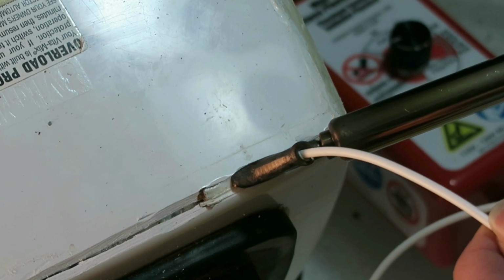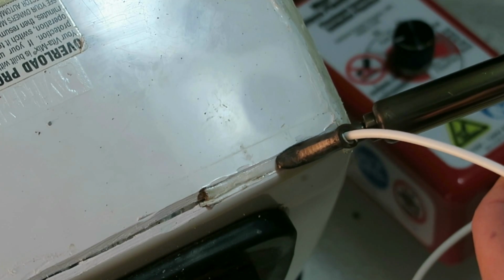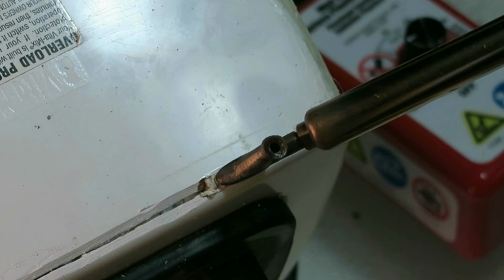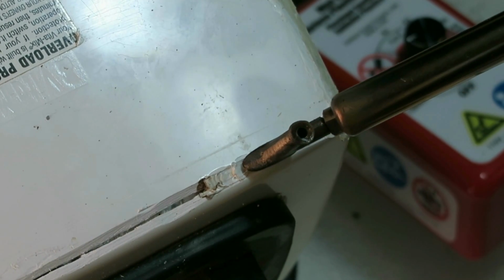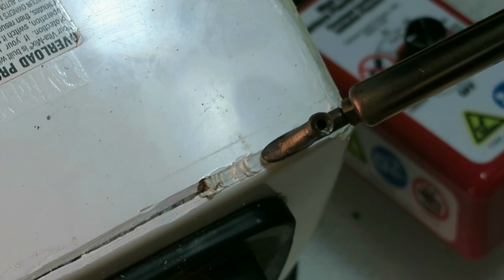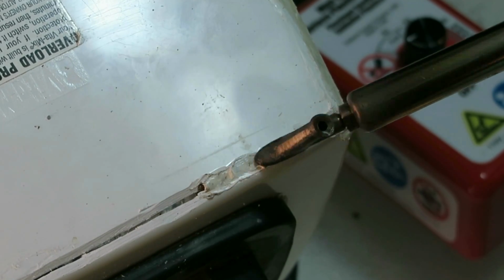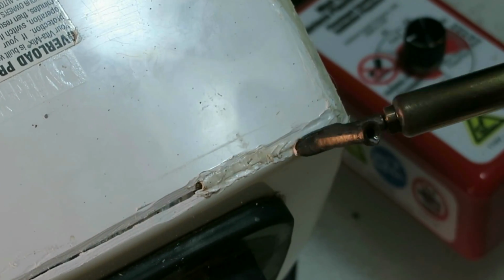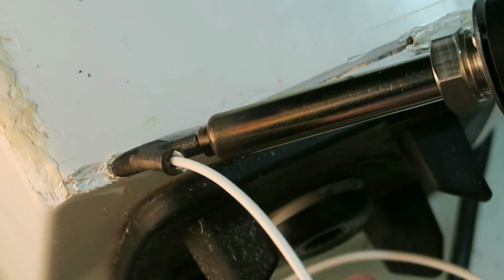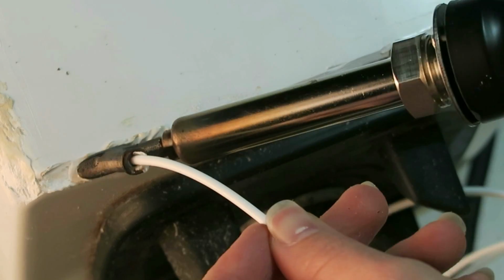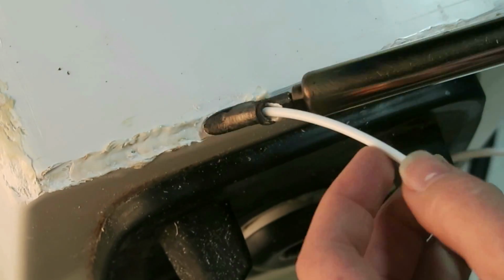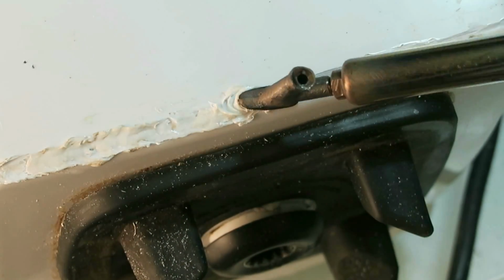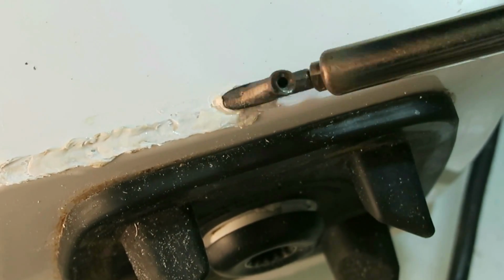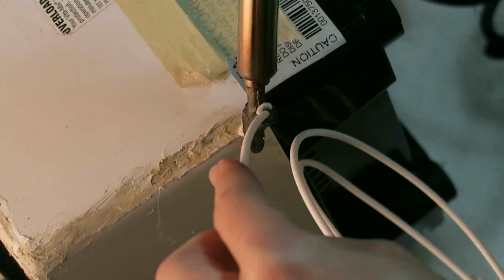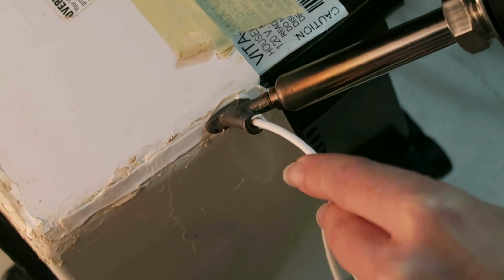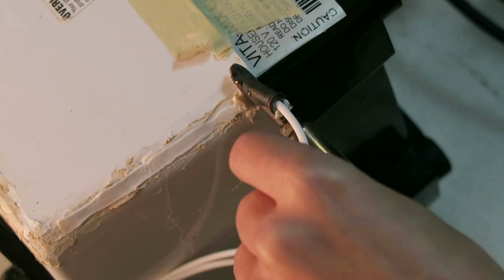On this bit, I'm trying to make a weld that looks nice, not discolored. This is the test area that we'll see later was least successful. It did not adhere because it was not melted into the parent plastic aggressively enough. At this corner, the temperature is still low, but I'm putting in the time and effort to melt the new plastic into the parent plastic. By the final edge, my hand is getting very fatigued because I've been applying so much pressure to mush and melt the pieces together with the relatively cool hot end.